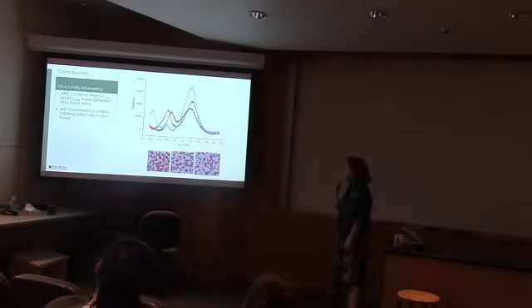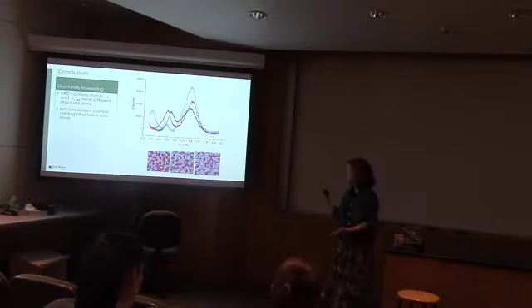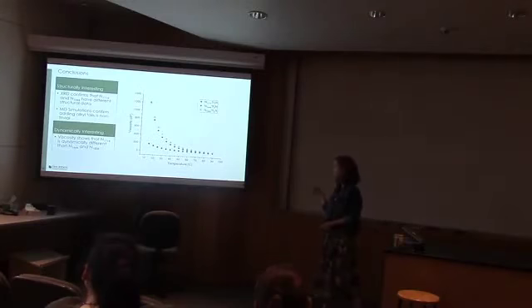So some conclusions. We know that these ionic liquids are structurally interesting because we have X-ray data that confirm the structure of 1114 is different than 1444 and 1888. And we also have these MD simulations that confirm that adding alkyl tails is not trivial. When we add more carbons, the phases change. And this is just an important conclusion. A dynamics conclusion that we can make is that our viscosity data shows that 1114 is just an outlier from the other two in a different way. It is much less viscous than the other two.